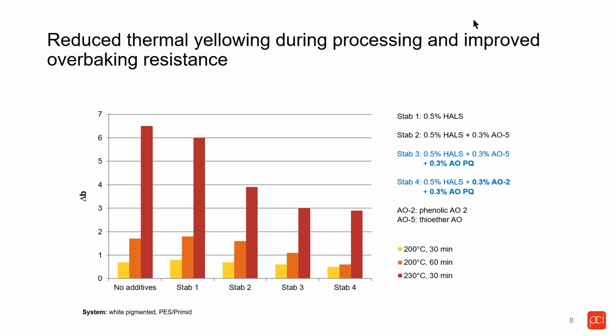What we see here is, again, at 200 degrees Celsius, which is your standard temperature, for 30 minutes, there are really no big differences when it comes to the yellowing of the system. Same here, white pigmented polyester primid. However, when we go to 200 degrees Celsius for 1 hour, we see that there is a difference. This is what we saw already in the previous slide. But if you do your overbaking test by increasing the curing temperature of your oven, the delta B, the yellowing, is significantly more while we are staying at 30 minutes of baking time.